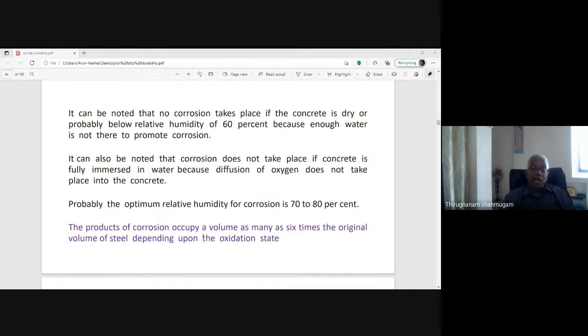The product of corrosion occupies a volume as much as 6 times the original volume of the steel, depending upon the oxidation state. So once the rust is formed and the steel is corroded, the volume of the corroded steel increases about 6 times. With a 6 times increase in volume, the surrounding concrete is completely disintegrated and falls off, and exposure to external agents is easily possible. The corrosion reaction proceeds further and further, causing corrosion of the reinforcement and complete failure of the structure.